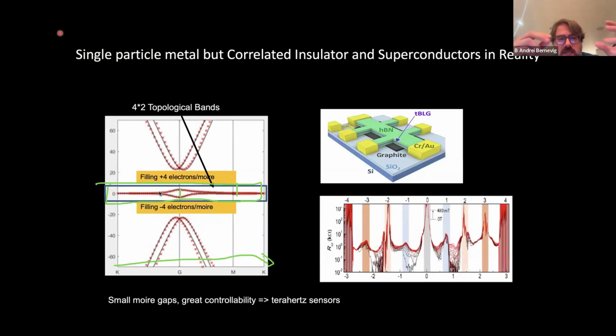So that's a very tiny proportion of electrons per the original graphene unit cell. But I also have 2 spins and 2 valleys, meaning valley K and K prime. So that's a factor of 4. So I can put 8 electrons in these bands, and the numbering of the band is going to be -4 in this single particle gap to +4 here, a difference of 8 electrons that I can fill these bands with.